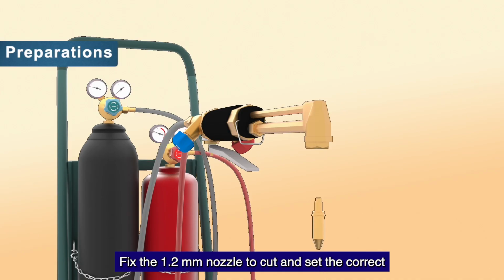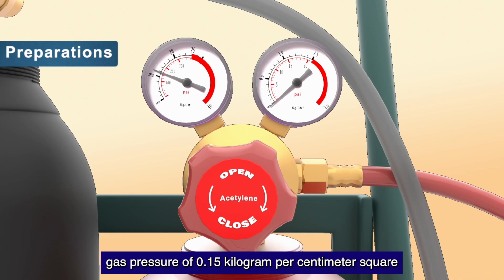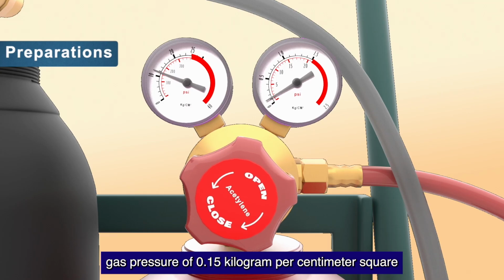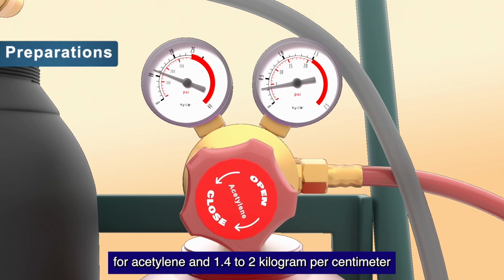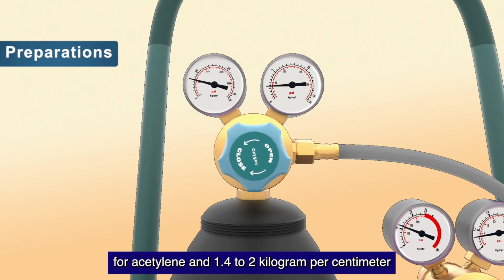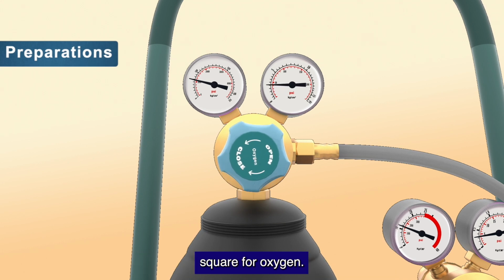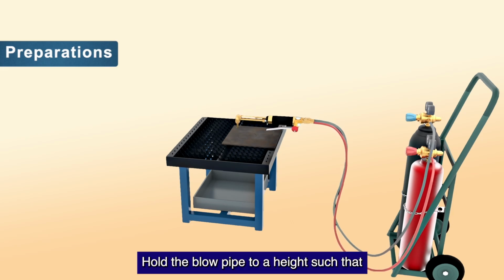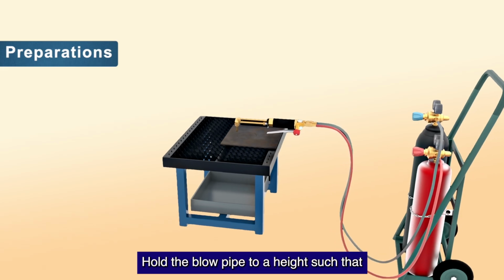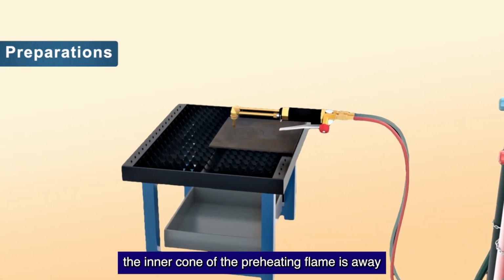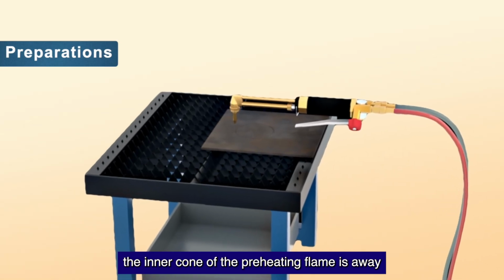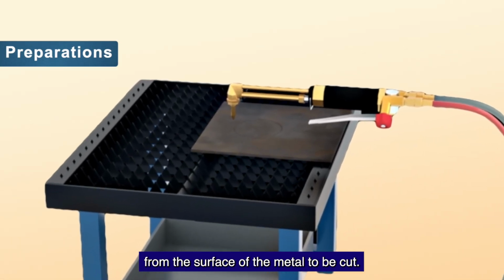Fix the 1.2 mm nozzle to cut and set the correct gas pressure of 0.15 kg per square centimeter for acetylene and 1.4 to 2 kg per square centimeter for oxygen. Hold the blowpipe at a height such that the inner cone of the preheating flame is away from the surface of the metal to be cut.